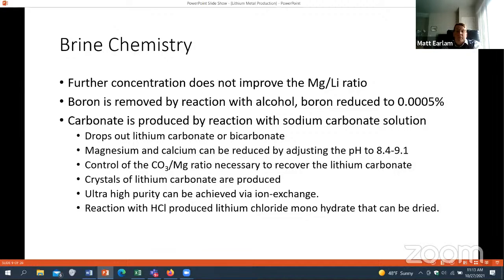The boron is removed by reaction with alcohol. And then the carbonate is produced by the reaction with sodium carbonate. It drops out lithium carbonate or the bicarbonate. The calcium and magnesium carbonates can be adjusted by controlling the pH at about 8.5. Controlling the carbonate ratio is necessary. As I say, crystals of lithium carbonate are produced. This is ultra high purity, can be produced by ion exchange, and then we react it with HCl to produce a monohydrate.